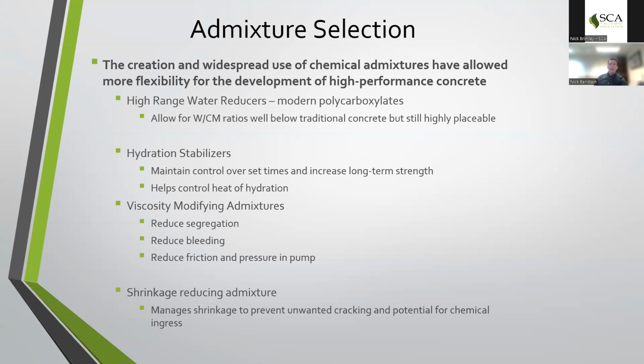Viscosity modifying admixtures are used slightly less, but can often help to reduce some of the more extreme placement issues that can come up, whether that be bleed from the mix design or potential for segregation if mix designs are traveling very long pump lines. This can also help reduce friction within the pump and overall pump pressures, helping for a more consistent and higher yards per hour moving through on job sites.